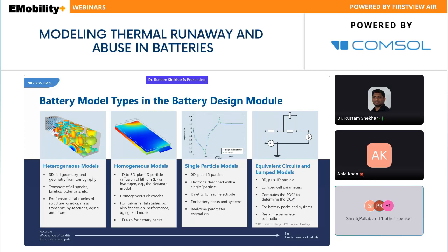In cases where you are not interested in the particle level detail, you just want to know in an overall sense how the battery will perform and how these failure scenarios will get triggered, then you homogenize it, and still you can account for the intercalation. That will be done by this 1D particle diffusion, which is intercalation, and which follows Newman's model. Then you can design the single cell, or you can stack them and make a battery pack. So in these homogeneous models also, you will model the homogeneous electrode and do the design analysis, performance analysis, aging, and many more. When we say more, that includes the internal short circuit or external short circuit. And lithium plating also, and gassing formation, all can be designed here.